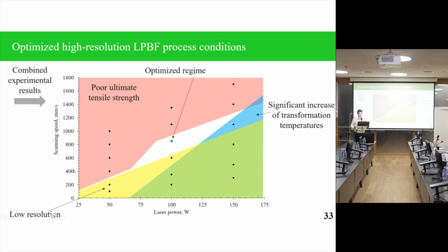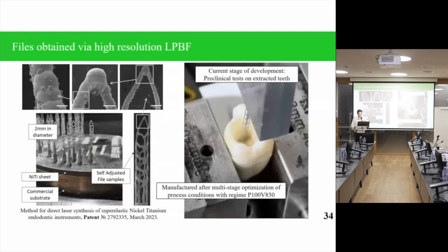So all regimes are presented again in scanning speed and laser power coordinates, and we can see that from the top side we have a limit because of poor ultimate tensile strength. From the other side we have a low resolution limit, and finally we also have a region where significant increase of transformation temperatures occurs. And finally, with the green point, we have the optimized regime. And these samples were received. We demonstrated that we can achieve enough resolution to print such files. And now this project is at the stage of mechanical tests also involving some extracted teeth.